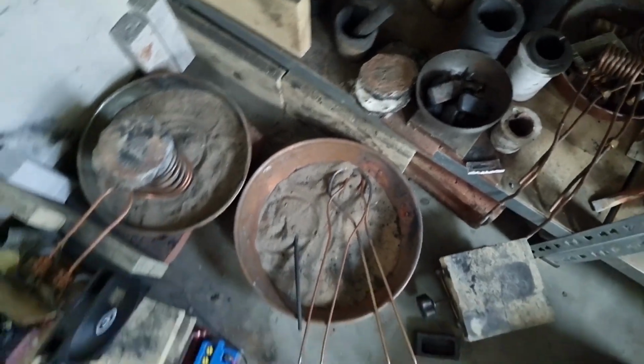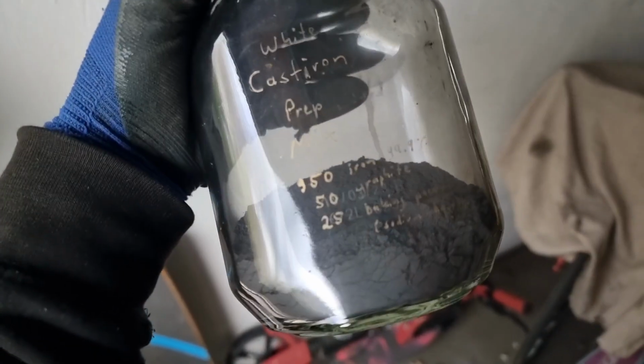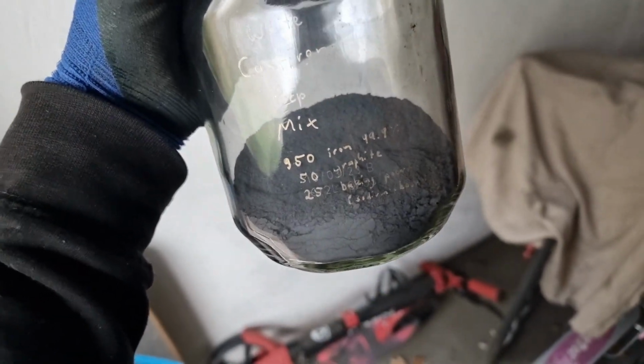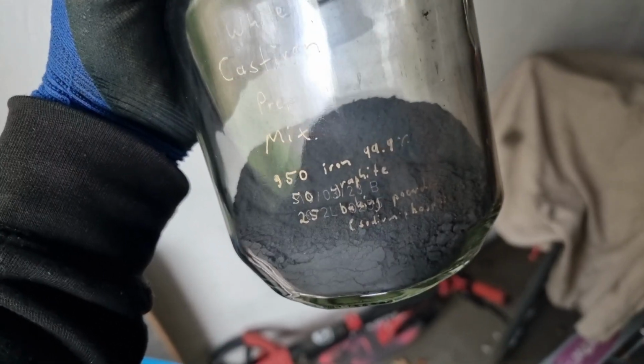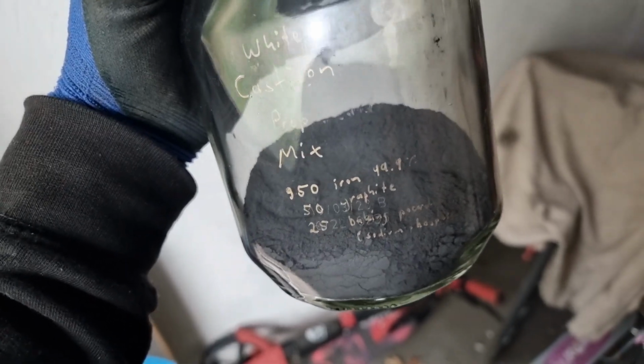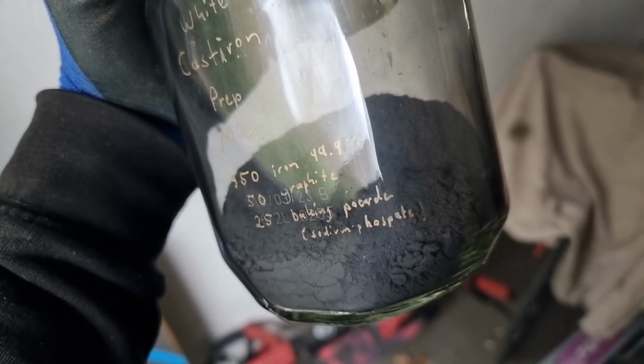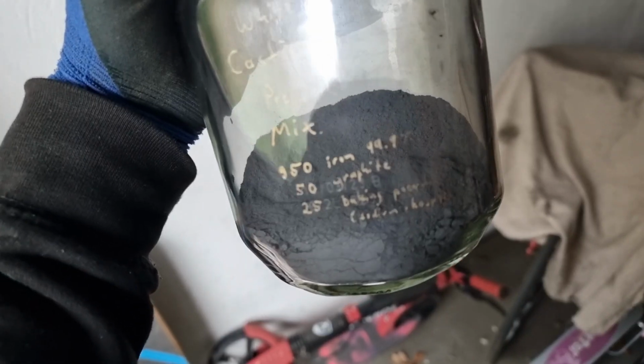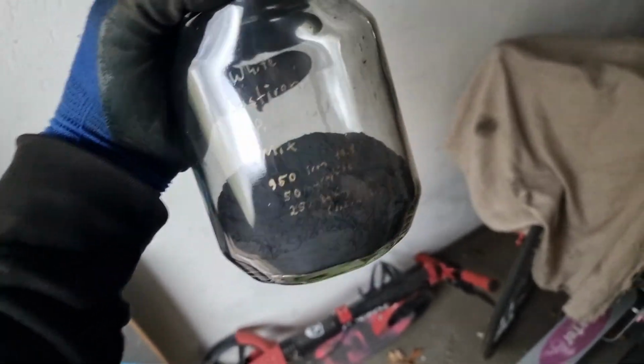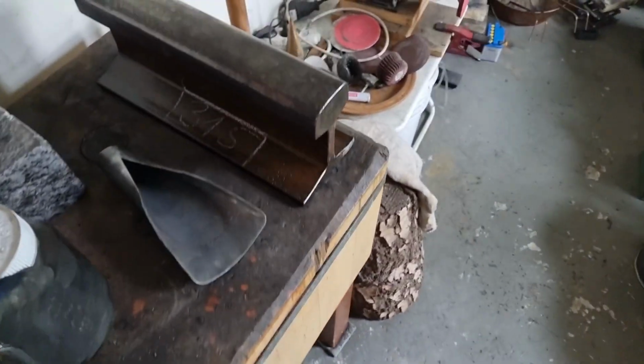And yeah, we start with a mixture like that one. So that is a mixture for white cast iron, and you see that is about, for 1 kilogram, 950 parts iron powder, so pure iron powder, 50 grams of graphite, and 25 grams of baking powder, which equals more or less pure sodium phosphate. That is in order to help the smelting process and also to make the cast iron more liquid, to reduce essentially the melting point a bit and make it more fluid.